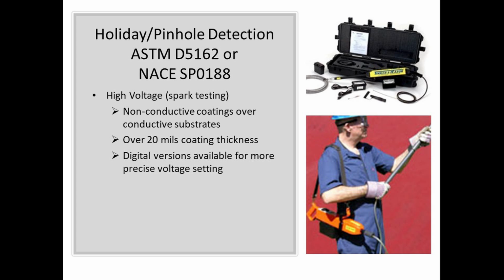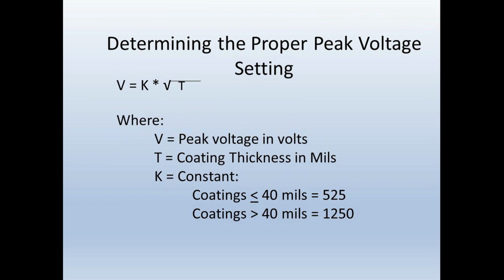With high voltage detection, it's really important that you calculate the voltage setting. It's a very simple calculation. All you have to do is take the square root of the coating thickness, the square root of the lining thickness, and multiply it by a constant. It's either going to be 525 or 1250, depending on whether you're below or above 40 mils.